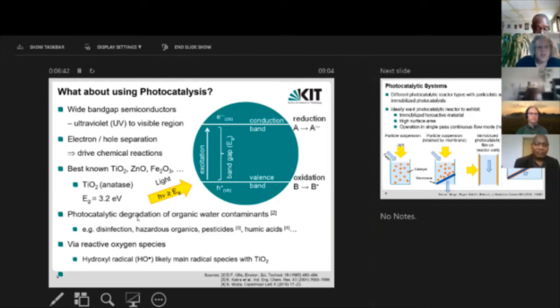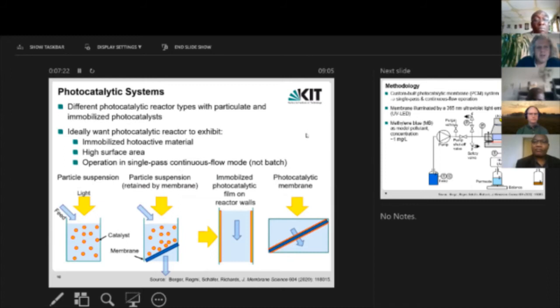Now, the overall goal here is that we want to achieve photocatalytic degradation of contaminants in water. This could be achieving disinfection, looking at getting rid of hazardous organics, as well as things like pesticides. And the main amount of work that is done by our titanium dioxide photocatalyst here, we don't have direct proof of this, but we suspect it's the hydroxyl radical ion that is the main reactive oxygen species present and active in our material. So when we look at these systems as engineers, you have a number of different types of photocatalytic reactors, and they could be either based on particles, as shown on the left, or they could be based on immobilized photocatalyst layers that are shown on the two right-hand examples.